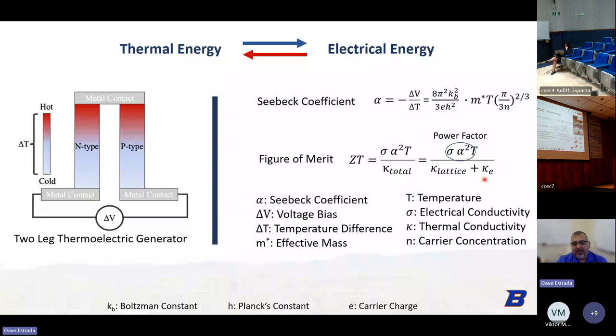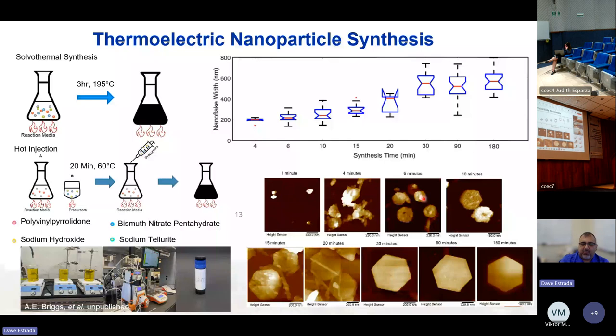Bismuth telluride was a material of interest just because of its Seebeck coefficient. The peak Seebeck coefficient is near room temperature, and so we set about generating bismuth telluride nanoparticles using solvothermal synthesis. This was a collaboration with Xiaofang Duan at UCLA, where we just take our reaction media and our precursors, bismuth and tellurium containing precursors, put those in a beaker, heat it up to 195 degrees Celsius, let the reaction occur for about 3 hours, then we can centrifuge this out, collect the particles, and do the analysis.